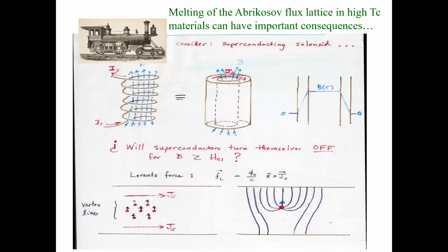But that magnetic field spills out into the superconducting wire. And if it's a type 2 material, and all these high TC materials are type 2, they have Abrikosov flux penetration in the presence of this magnetic field, then the flux lines will move, dissipate energy, and your train will come crashing down onto the tracks. That's an issue with superconducting applications that's known for a long time.